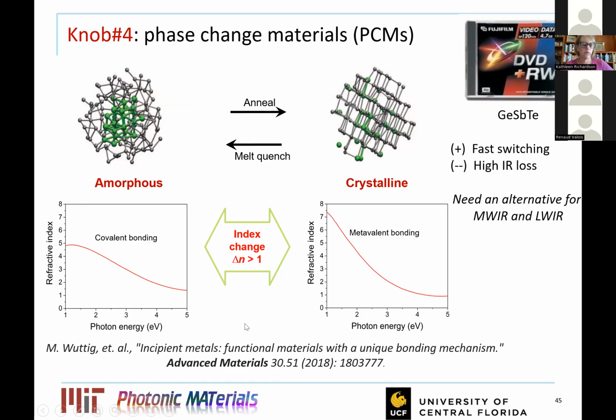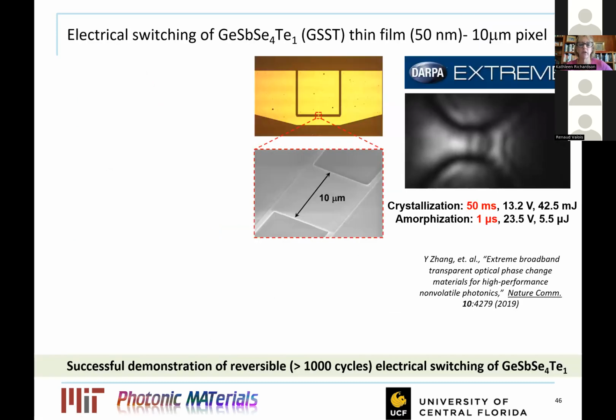And typically, this is work from Professor Wuttig in Aachen, who wrote a wonderful review of these materials. They go through a change in types of bonding, which gives rise to a wide range of refractive index changes, as well as thereby reflectance and transmission. You're familiar with these because germanium antimony telluride is the historic legacy phase change material, which is commonly used in read-write DVDs. But for work in the mid-wave and long wave, these materials are too absorbing. They were engineered for fast switching times, which they need for that application, but unfortunately they have good switching but high infrared loss. So we needed to engineer other materials.